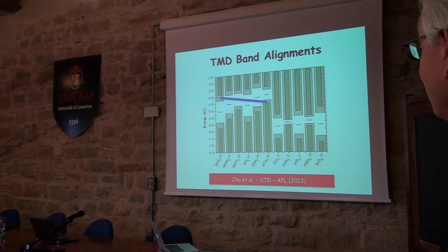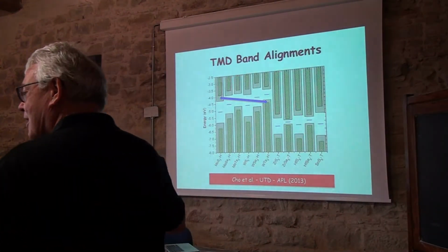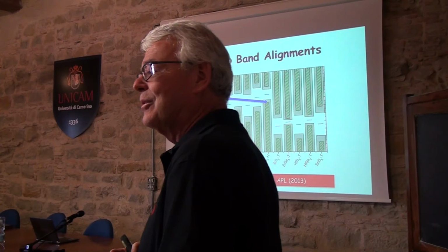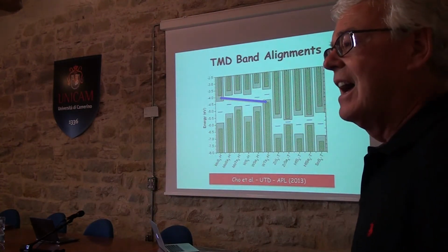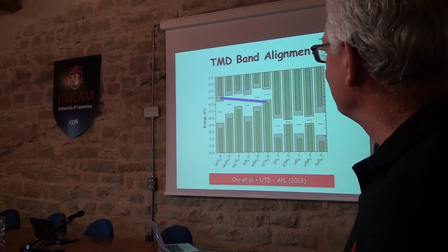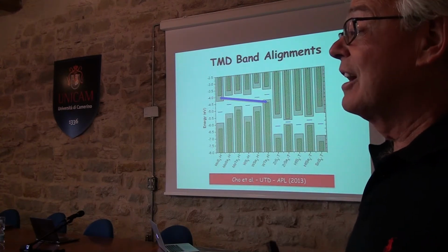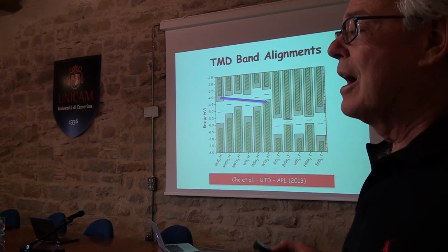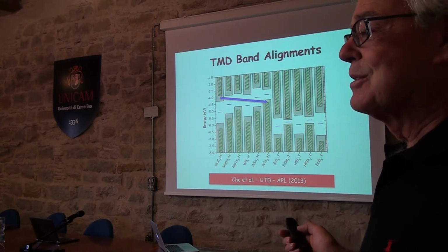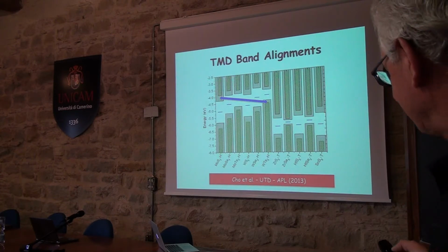And in these transition metal dichalcogenides, in the BEC BCS crossover problem, the maximum TC you can get scales with the exciton binding energy. And the exciton binding energy in these transition metal dichalcogenide two-dimensional semiconductor layers is somewhere between 0.5 volt and 1 volt. So you have a big starting energy scale to work with. So as Alex was saying, the materials are nowhere near good enough at the moment, but maybe you can get there.